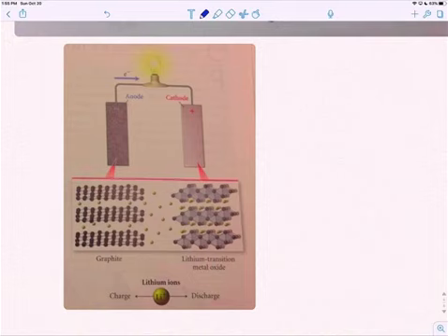So when you charge the battery, of course, what happens is the lithium ions move from the cathode back to the anode. And if you keep on putting that really negative charge on it, what happens is the lithium ions reduce to lithium metal, and then they react with the interstitial fluids of the battery, and it destroys the inside of the battery that way. So that's the reason why they go down.